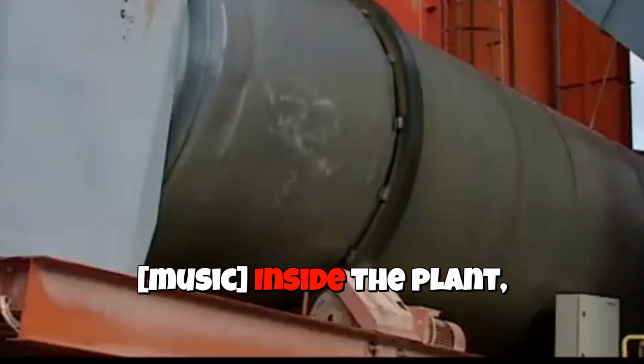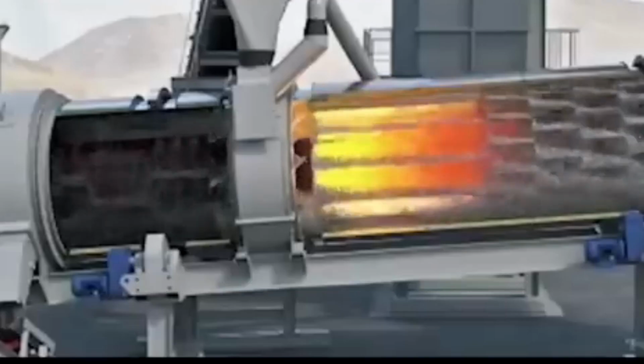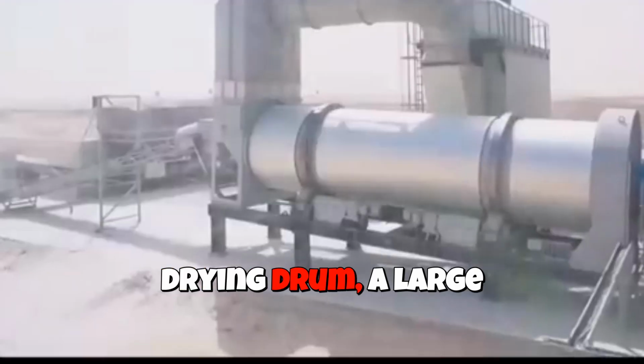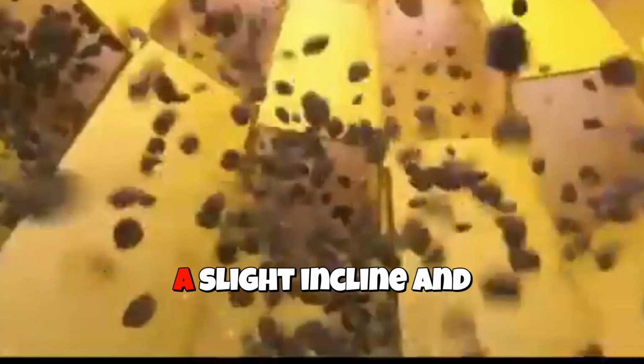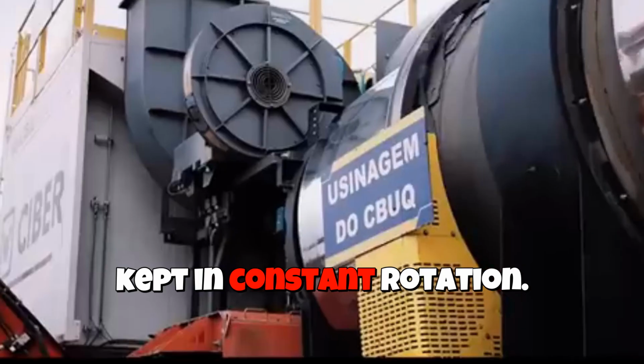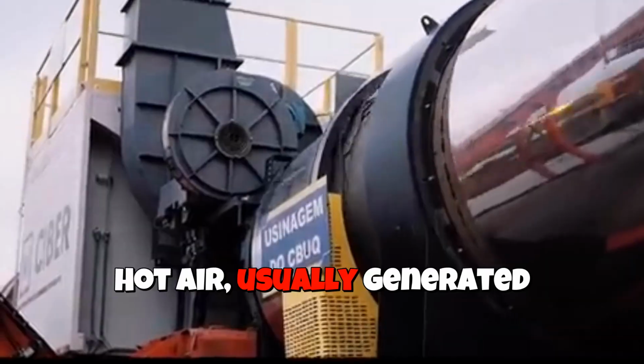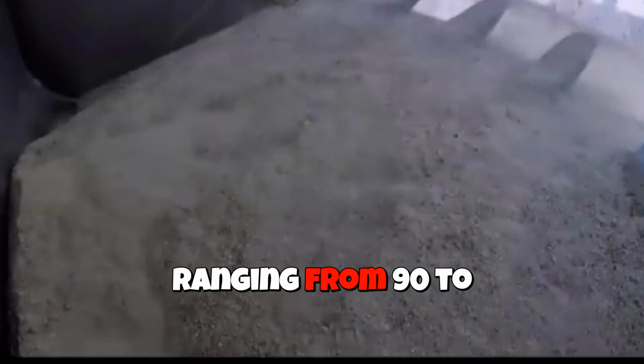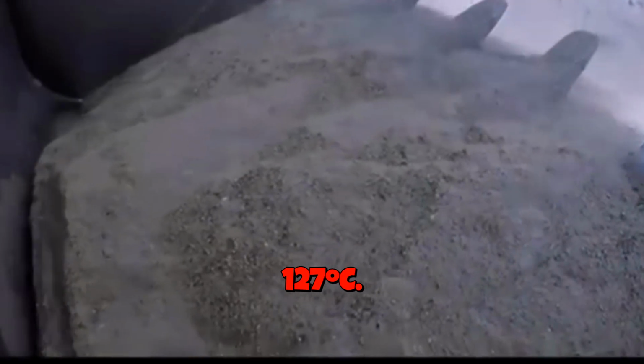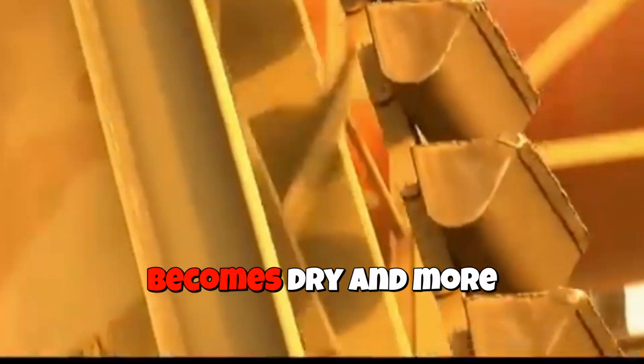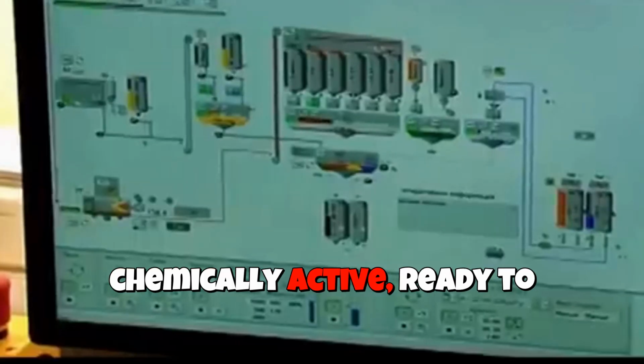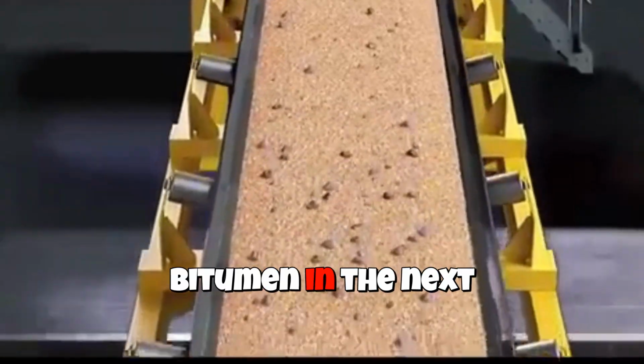Inside the plant, the rubber granules are introduced into a rotary drying drum, a large steel cylinder placed at a slight incline and kept in constant rotation. Hot air, usually generated by burners fueled with natural gas or fuel oil, is introduced into the drum at temperatures ranging from 90 to 127 °C. As the material flips inside, moisture is progressively removed, while the surface of each rubber particle becomes dry and more chemically active, ready to interact with the hot bitumen in the next stage.